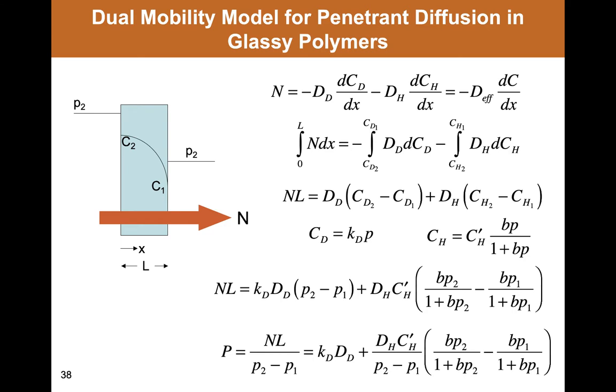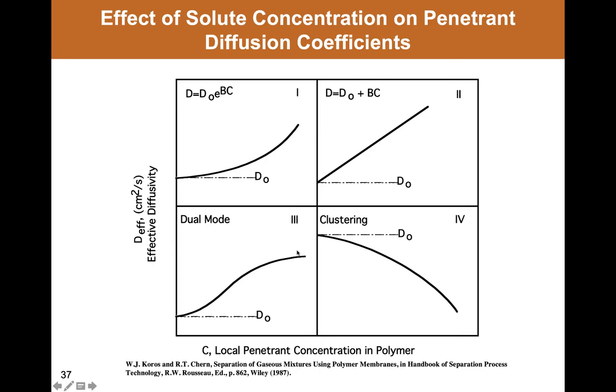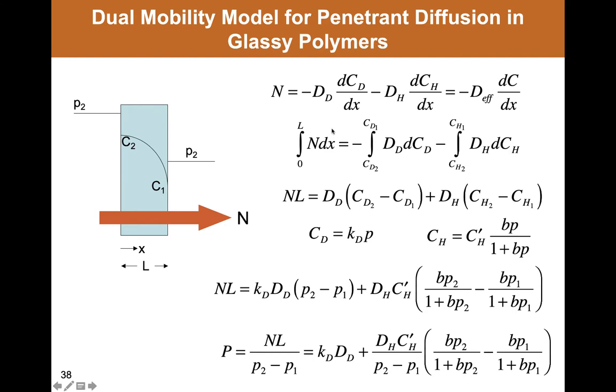One thing that I'll note about the so-called dual mode model, which is for gas transport, small molecule transport in glassy polymers, is that it postulates, we've already seen the solubility model, where we postulate Henry's law and Langmuir modes for solubility. This is what gives the sorption isotherms their concave appearance relative to the pressure axis. There is a transport model that goes with that, and I'll just present it very briefly here. And it presupposes that the flux of penetrant through a glassy polymer also consists of two components. One is flux through these Henry's law or so-called dissolved gas regions, and a flux through the Langmuir regions. And each of these modes, Henry's law and Langmuir mode, can have different diffusion coefficients in this particular model.